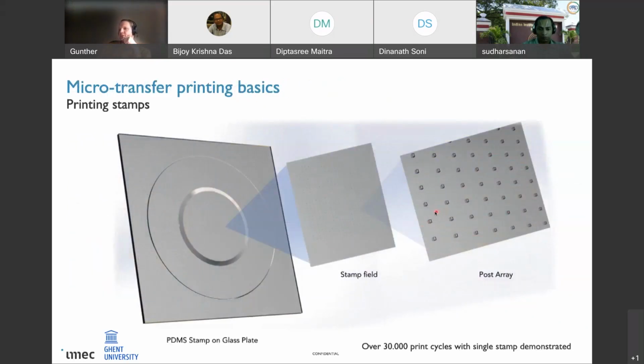Now, the stamp that is used to pick up and print these components is made out of PDMS. PDMS has several advantages for this application. First of all, it is transparent, and as you will see later on, we will use this for the alignment process. Secondly, you can cast PDMS on a master and then basically make structured stamps. So you can, in the PDMS, create an array of posts on a particular pitch for your application, which allows you to pick up a subset of III-V components from the III-V source wafer and print it to the target wafer. Now, these stamps are quite robust. Over 30,000 print cycles with a single stamp have been demonstrated.